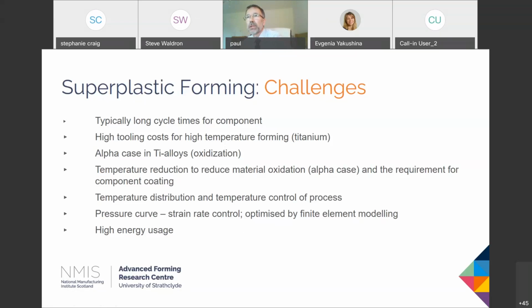Just staying on this slide for a second, in the case of titanium specifically, because we're forming at very high temperatures, the tooling needs to be stable at those high temperatures, and therefore the sort of tools that we use are very highly alloyed, so they're quite expensive. The titanium itself can be subject to oxidation. It forms something called alpha case, which needs to be then either milled or chemically pickled off. So that adds an extra stage to the process.